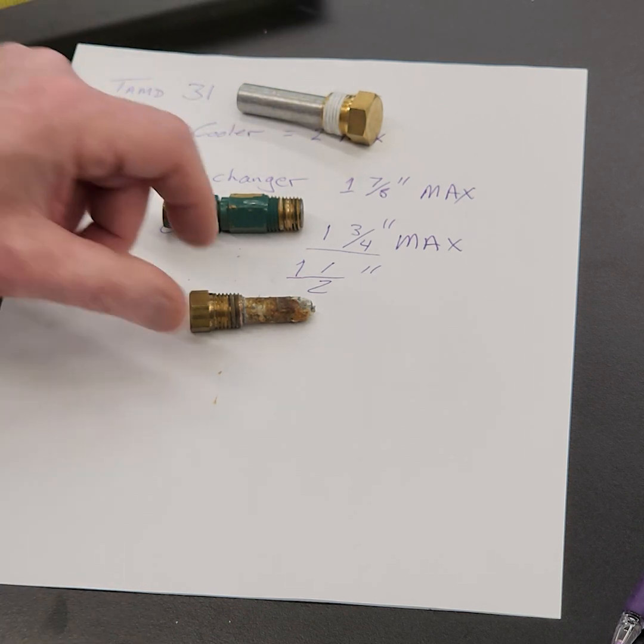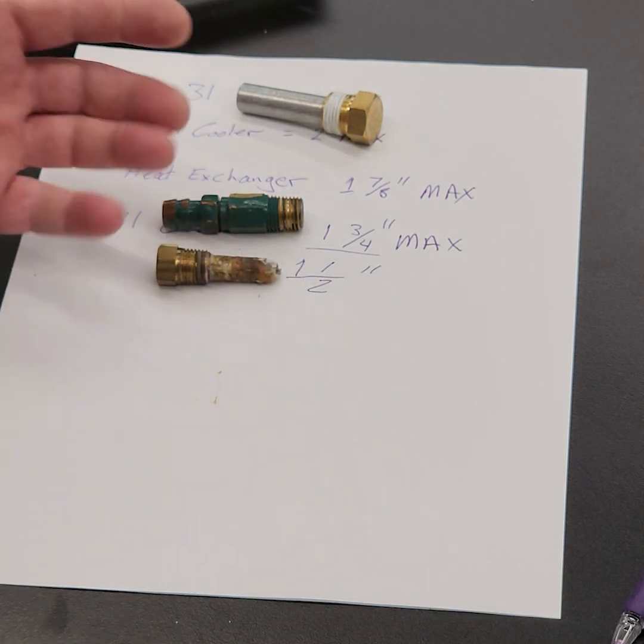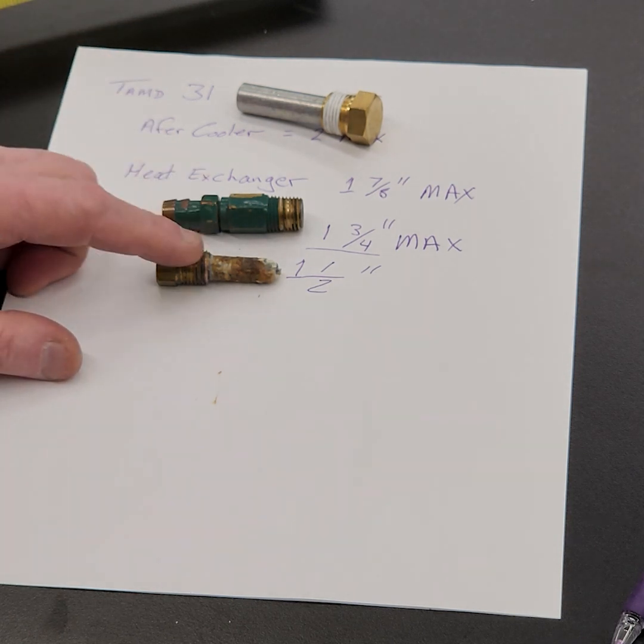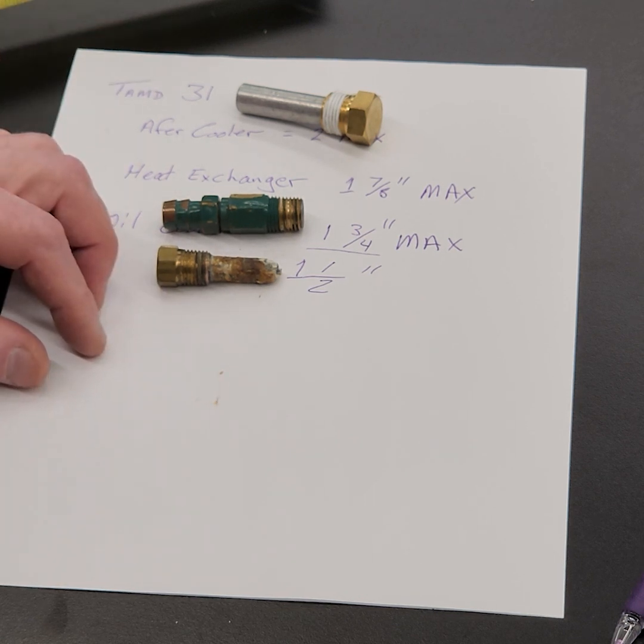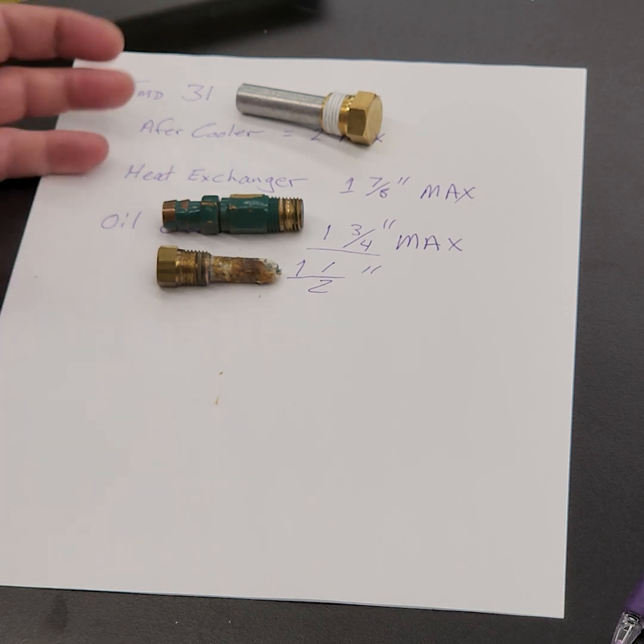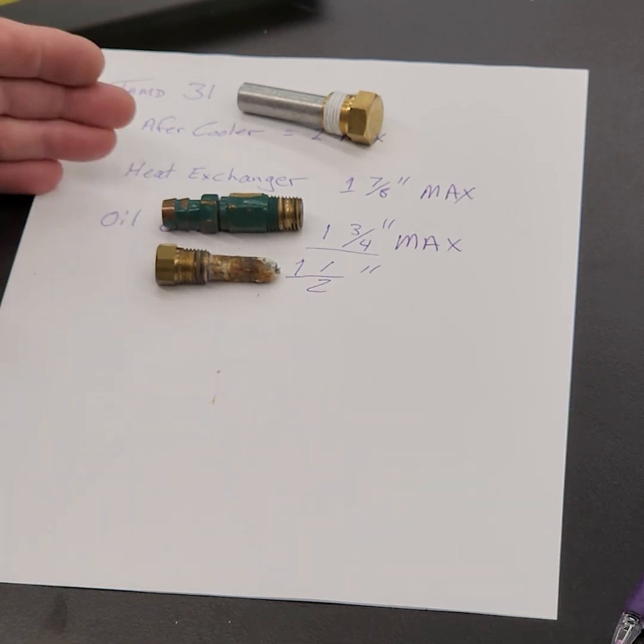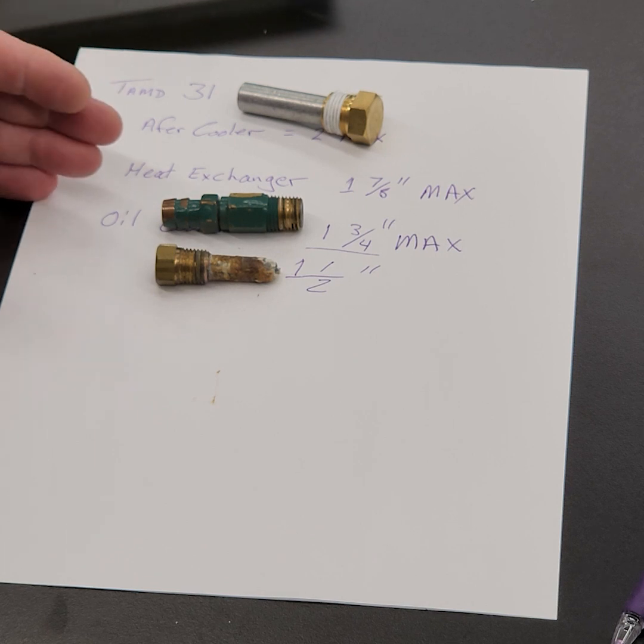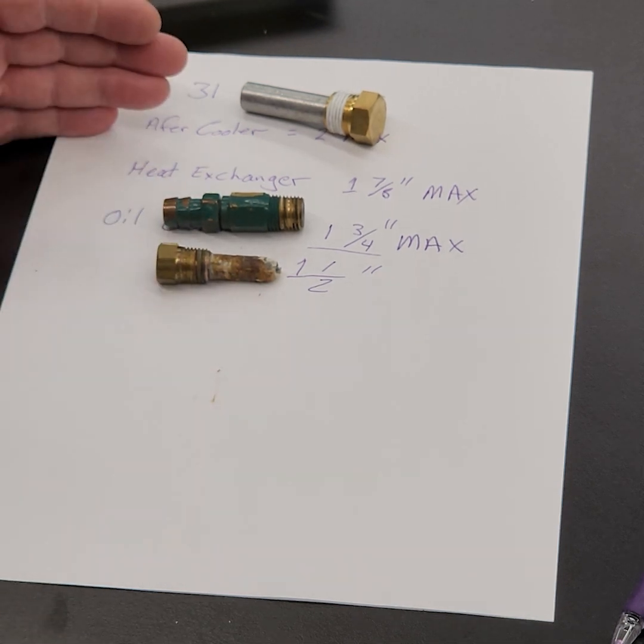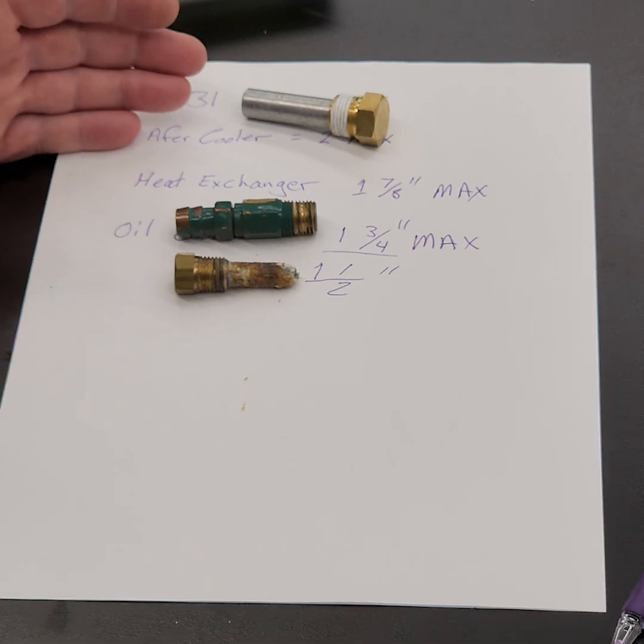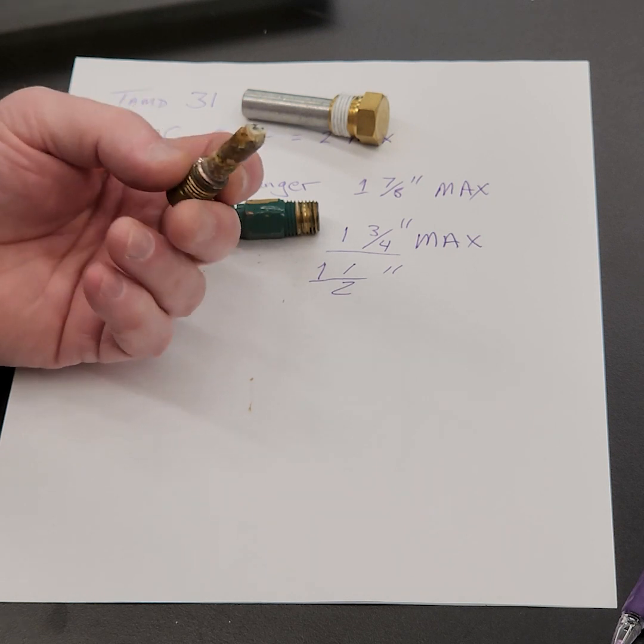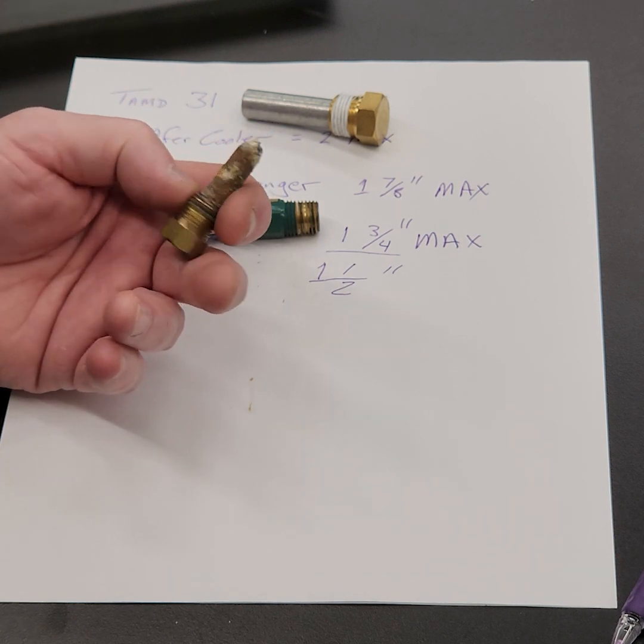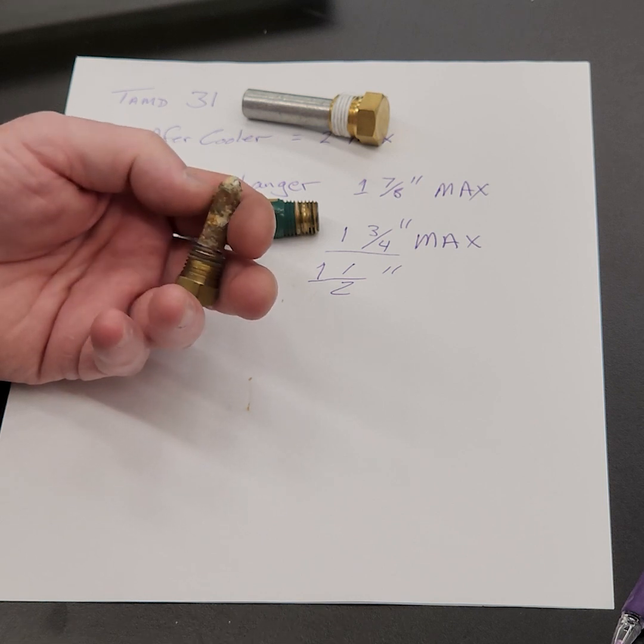Due that they're going to be small, they'll probably corrode away reasonably fast. So in this application, I would probably want to inspect these halfway through the season. So if the boat up here in the northeast goes in the water in April, May, somewhere in there, if it's really early, even up to June, then halfway through the season, I would say two months, two and a half months. So if you go in in May, June, July, I would say middle of July, you should check that anode. And if it looks like this, it's over half corroded, then you should change it.